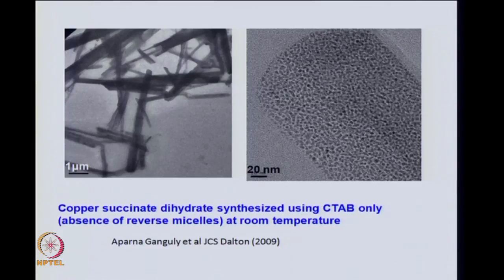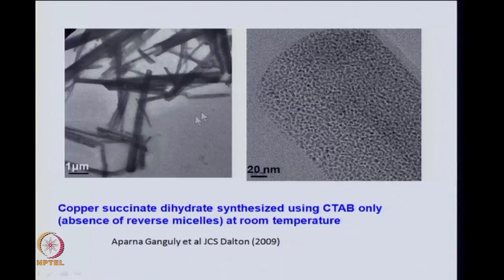The crystallinity disappears, and if you look carefully, you can see these particles, and these particles under high resolution can show you these lattice fringes, and on decomposition they will give you copper oxide, like they can be obtained from copper oxalate. So, again we show you the same copper succinate dihydrate synthesized using CTAB in the absence of reverse micelles at room temperature, and they are slightly different. And if you use the reverse micelles, you are getting these crystalline rods, whereas you can change the morphology of these rods by choosing whether you want to do it in reverse micelles or in the absence of reverse micelles.